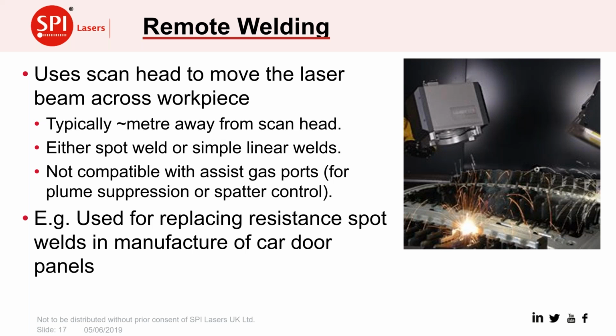And a fairly well-established application for laser welding with scan heads is called remote welding. Generally, the heads are about a meter distance away from the workpiece. It does give a fairly good area over which the beam can be directed. Generally, we're using that for a spot weld or for short linear welds. And one application here is replacing resistance spot welding for the manufacture of car door panels, where all the welds around the edge of the door are done in a remote weld application. Obviously, in this case, you can't really use a shield gas because of the distance, so you've got to live with any plume or spatter that comes out from the process.